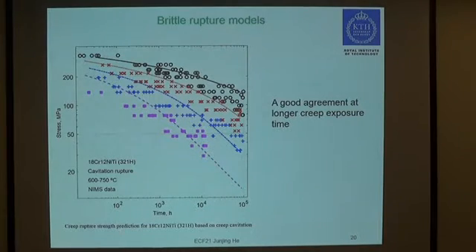Here we show the results for the brittle rupture models. And this is the creep rupture strength as a function of creep time. It's for 321 austenitic stainless steels. The experimental data here is in a range of 600 to 750 with 50-degree intervals. And the experimental data is from NIMS in Japan. The modeling results here are based on the creep cavitation models. So at a longer creep exposure time, it can reach a good agreement.